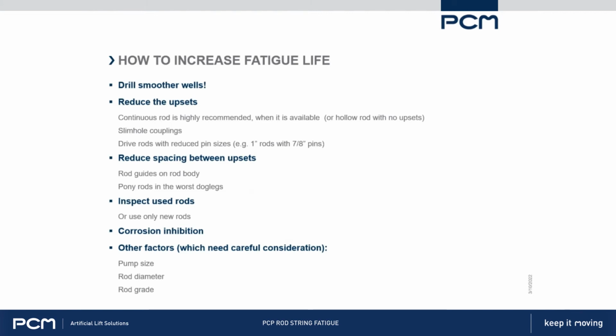But even if you're buying other sizes of rod, for example, 1.25" rods or 1.5" rods, there is no 1.25" or 1.5" couplings out there. So those rods all have couplings that are no bigger than 1 1/8. So 1.5" rods typically have 1 1/8 inch connections on them. So it's already a reduced. 1.25" rods can come with 1-inch connections or 1 1/8. So obviously 1-inch connections, they might not have as high a torque capacity, but if you make them up properly, they're still as strong as the rod body. So using that, you get a smaller diameter connection. Always a good idea to keep that connection small.